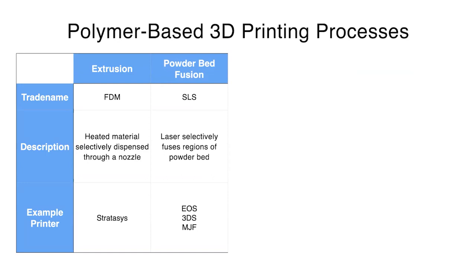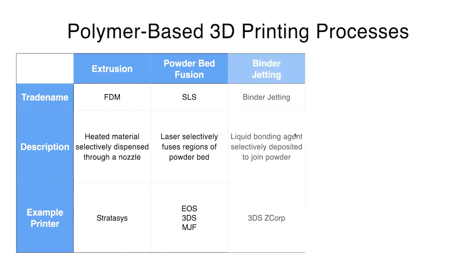But as you know, with polymers, there's essentially no entropic force for mixing. Low surface energy, and diffusion is really on a long length scale, especially at high molar mass. And polymer properties are all derived from chain entanglements. When you transiently heat something up for a short period of time, you don't evolve the chain entanglements like you do in conventional injection molding-like processes. But nonetheless, it's gotten some traction for sure.